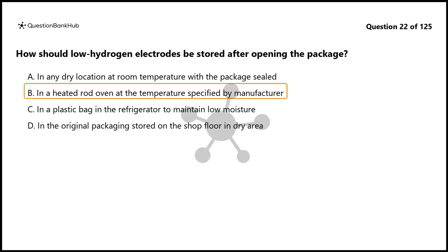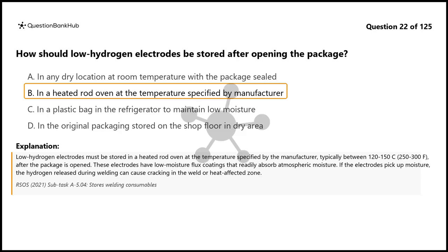The correct answer is B. In a heated rod oven at the temperature specified by manufacturer. Low hydrogen electrodes must be stored in a heated rod oven at the temperature specified by the manufacturer, typically between 120 to 150 C, 250 to 300 F, after the package is opened. These electrodes have low moisture flux coatings that readily absorb atmospheric moisture. If the electrodes pick up moisture, the hydrogen released during welding can cause cracking in the weld or heat-affected zone.